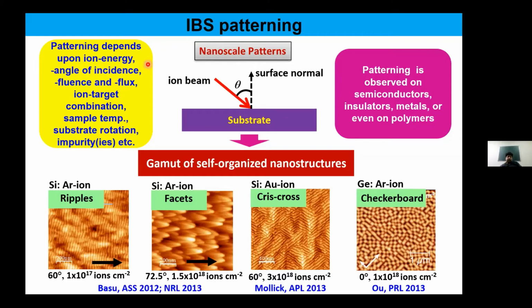For instance, I have shared here different and beautiful patterns that are generated in laboratories. Many of these patterns have been successfully generated by us, and some were reported by some other groups as well. You get to see here that the leftmost frame, where we have written ripples, is on the silicon surface, using very low energy argon ions, 500 electron volt of argon ions. Here we have utilized sub keV ion energy, 500 eV. We have also gone down to 250 electron volt of ions.